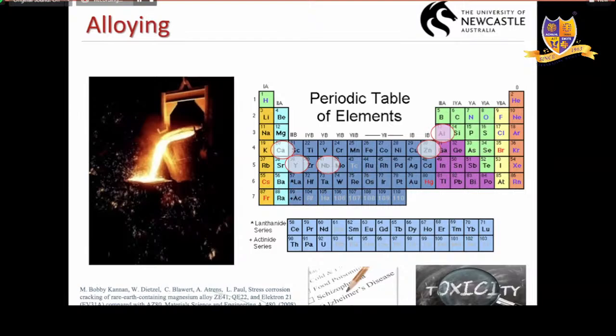And unfortunately, alloying of magnesium is not as simple as in steels because of its highly reactive nature. And alloying is done at a very high temperature, at its melting point. We are talking about 660 to 670 degrees centigrade. So when it is exposed to air, it will just catch fire. So you have to do it in an inert environment. And when you do alloying, you can't just add XYZ into it. You have to understand the solubility of these elements as well. And mostly magnesium has low solubility with these elements. So it is narrowed down to only a few elements which I've highlighted here.